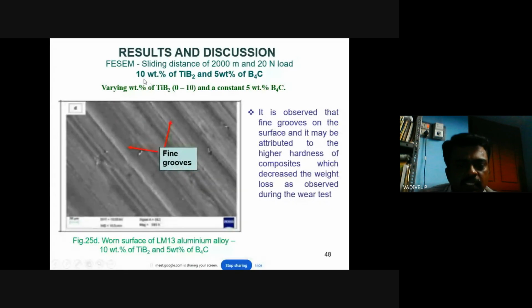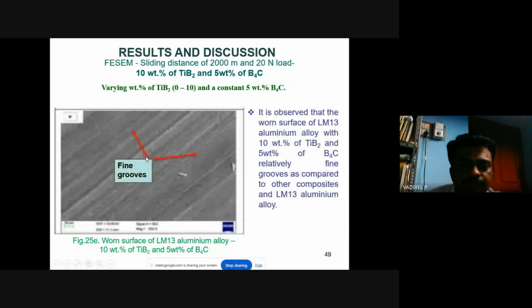And the next one is 10% of titanium diboride and 5% of boron carbide. So here you can see fine grooves on the surfaces, and it may be attributed to the high hardness of the composites, which decreases the weight loss as observed during the wear test. So you can see the fine grooves here.